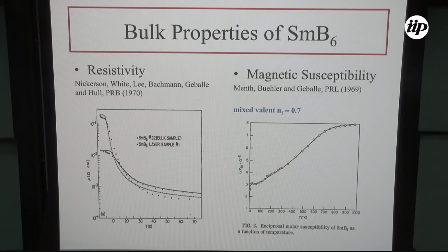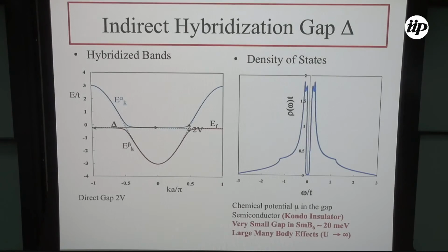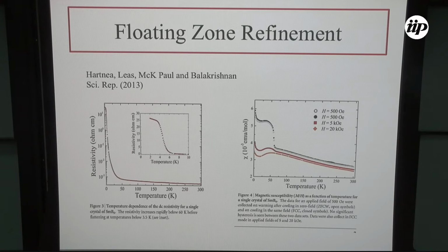The inverse magnetic susceptibility follows a Curie-Weiss law, and then it folds over at low temperatures. There's the little spike here, which may be intrinsic. With better samples, you still see this plateau at low temperatures, and this is the thing that's caught people's attention, with the topological nature.